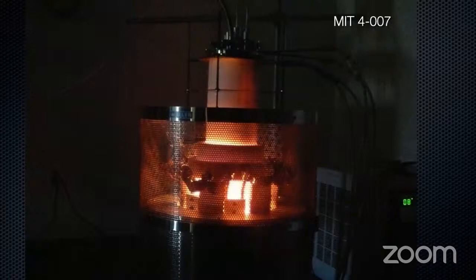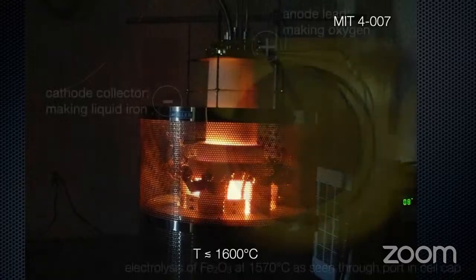This is the basement of MIT. This is a molybdenum disilicide furnace. Up here at the top, you can see the cell cap with feed-throughs, electrodes coming down. The action is way, way down here. This is an alumina tube, and the alumina tube is actually acting as a light pipe. It's white heat down at the bottom here. And so we were doing the work. This is 1600 degrees C.